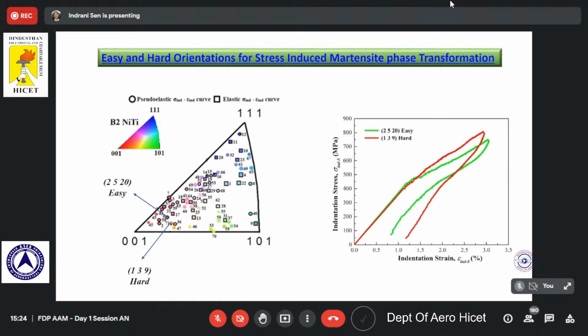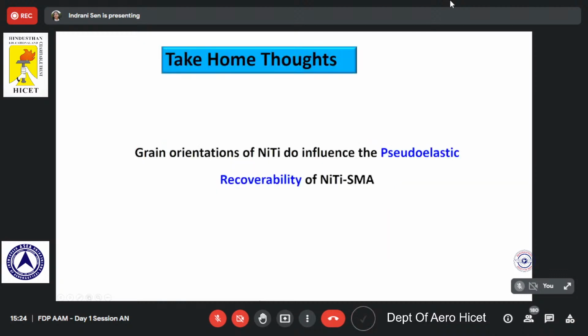So based on this kind of detailed study, we have done this on hundreds of grain orientations to figure out which one is the easy orientation, that means which shows the best pseudoelasticity, and which one is the hard one. So the take-home message from here is that grain orientations do influence the phase transformation characteristics and the pseudoelastic recovery. And if we are thinking of using it for a single crystal application, we should be careful about that.